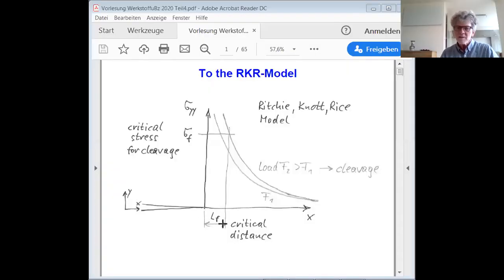However, unfortunately, if you make tests in materials, you find that LF is proportional to 2.7 times the grain size or to 1.8 times the interparticle distance. And so that is the problem of the model, that you have no clear physical meaning of that critical distance LF. Therefore it seems that the RKR model, although it is so convenient to use and rather simple, is probably too simple to describe reality. Okay.